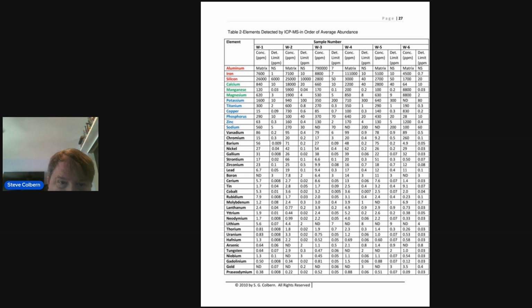We have calcium, manganese, magnesium, potassium, titanium, copper, phosphorus, zinc, sodium. It's hard to get a feel for all this without staring at it for quite a while. But there were some rare earths here too, which I found interesting. I heard a while back they were doing experiments to strengthen aluminum using rare earths. So perhaps that was part of the reason for their presence. There's gadolinium, praseodymium, neodymium, and a couple other rare earths, I think, too. Next page.